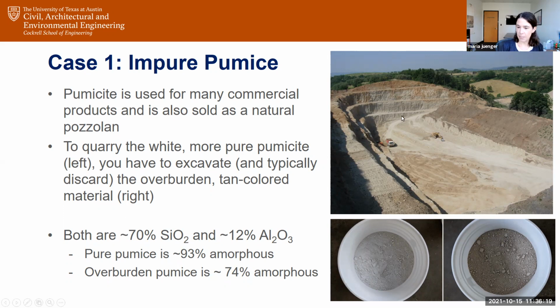And typically what happens when you have a quarry and you're quarrying material, you have material at the top that's mixed with other minerals. It may not be as pretty and it's not as compositionally pure. And so you get something that, in this case, the manufacturer is calling tan. So the tan pumice. They're both pretty good, very high in silica and alumina. So they meet that criteria that we have.